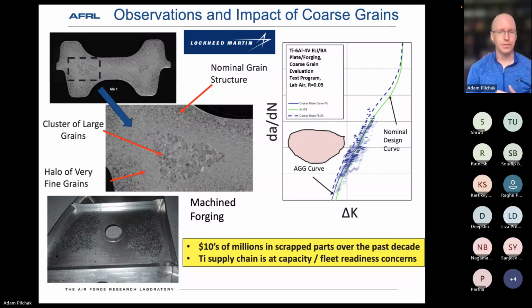And so this has resulted in lots of parts being scrapped. And at the time we were working on it, there seemed to be an uptick in the number of rejects due to this condition. And also at the time, and actually persisting into today, the lead times to get titanium billet are quite long, approaching a year in some cases, and so there's programs that are waiting for these forgings, and then they get the news that they're non-conforming and have to wait a whole lot longer.